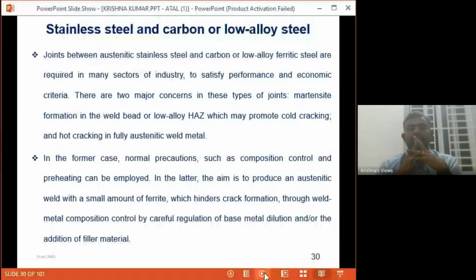There are two major concerns in these types of joints. One is martensite formation in the weld bead or low alloy heat affected zone, which may promote cold cracking, and the other is hot cracking in fully austenitic weld metal. In the former case, normal precautions such as composition control and preheating can be employed. So, in order to avoid this, we can do preheating before execution of the joints.